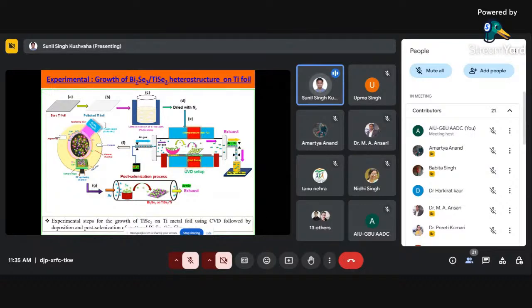So what we have done here, we again use this titanium foil. Without doing any electrochemical anodization, we have done only formation of the TiSe2 with a single zone furnace. We have selenium powder and put the Ti foil at different heating temperatures, like 500, 450 degrees Celsius. After that, we get very good TiSe2 nanopyramids. Then of course we coated with some bismuth selenide materials. I will just show that one.